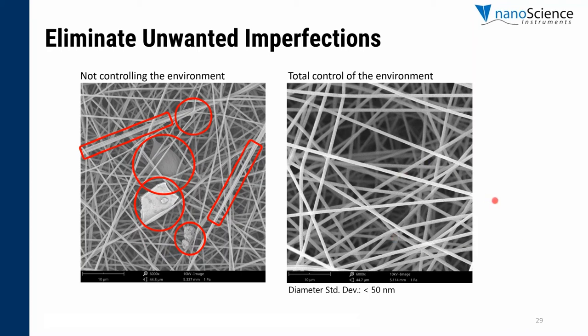And then as you can see in this right image, fiber diameter is uniform and even the standard deviation is less than 50 nanometers, which is really, really impressive. So by controlling all global parameters, you will have consistency over and over. And again, when using the climate control unit, controlling every single global parameter and after everything is optimized, you're gonna have batch-to-batch consistency and then you can eventually scale up to production if needed.